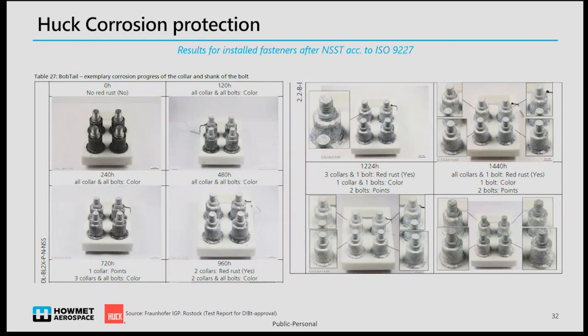So besides the general spec for our coatings, we have also results for installed corrosion performance. So for example, here you can see the results after 1,440 hours in a salt spray test for the bobtail with a zinc flake type of coating.